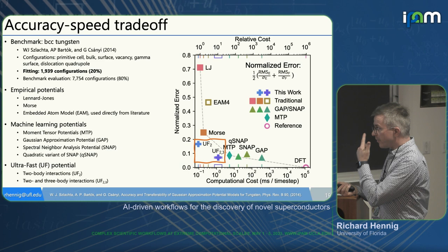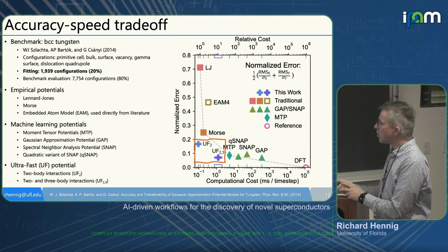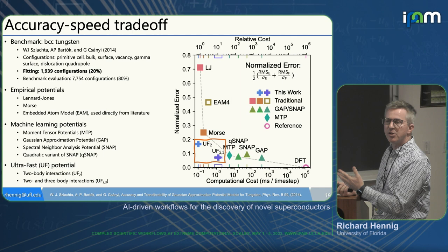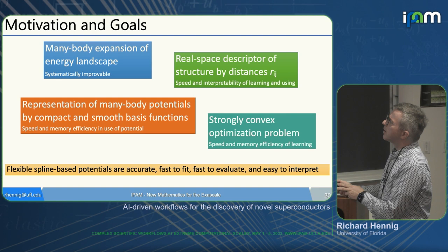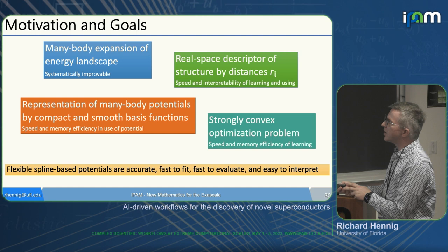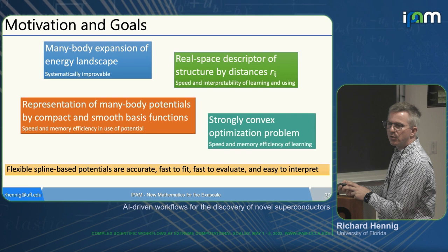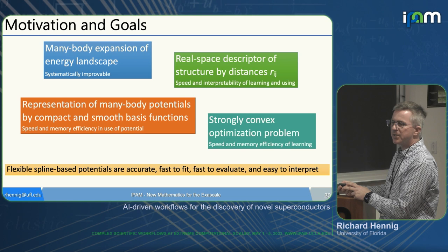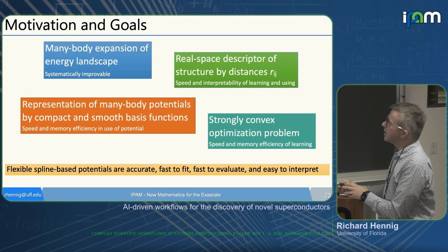This method, put together in 2019 at the IPAM workshop, is actually very similar in spirit to what Ralph presented. We had several motivations: first, we wanted it systematically improvable, starting from the exact same many-body expansion of energy landscapes. We felt that a real-space description of structures by looking at distances R_ij between atoms is ideal, because when you look at any molecular dynamics code, this is the one property the code already has. We wanted to avoid Hermite polynomials, spherical harmonics, and other such functions because that's extra calculation we didn't want to do.